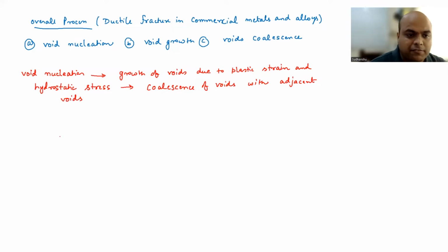Okay, that means if I have a material, suppose you are doing a tensile test itself, right? So you have a material and then you have some second phase particles, right? I've shown you one of the microstructure images of an aluminum alloy where you can see those second phase particles. So suppose you have these second phase particles. What will happen? You are going to generate voids in the second phase particles, and they are going to grow with time, with strains.